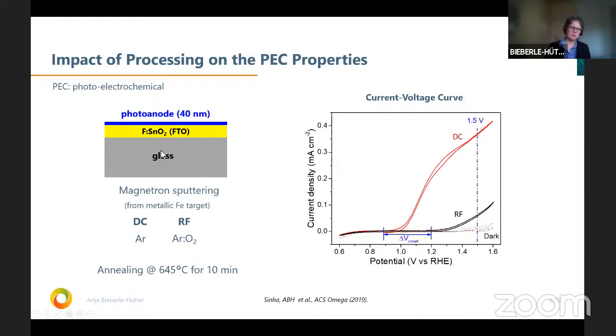And what you see here is a cross section. We use the typical substrate, glass with an FTO layer, and then on top a photoanode that we prepare by two methods, which I show in the following: DC sputtering and RF sputtering. DC sputtering is in an argon atmosphere, then we anneal to get the oxide. RF sputtering you do in an oxygen-rich atmosphere so that you deposit already an oxide. All samples are annealed at 645 for 10 minutes in air.